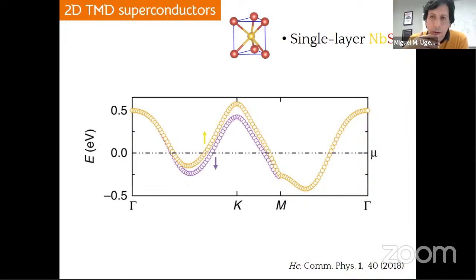Okay, so today I will focus on single-layer niobium diselenide and not on tantalum diselenide. I know that in the abstract I also talked about tantalum diselenide, but we are still studying it, and we believe that it's a bit more complex than the case of niobium diselenide, so I don't want to mess it with it. So we'll focus on niobium diselenide, which has a simple band structure in the single-layer limit. This is the only band that crosses the Fermi level, the only band that matters in terms of the superconductivity. As you see here, this band splits at particular regions in the Brillouin zone, in particular here close to the K point, due to the presence of the spin-orbit coupling.